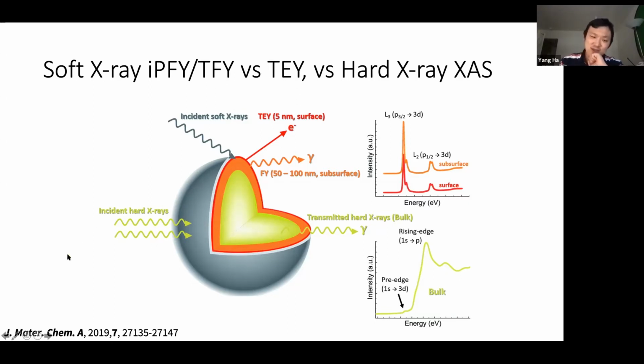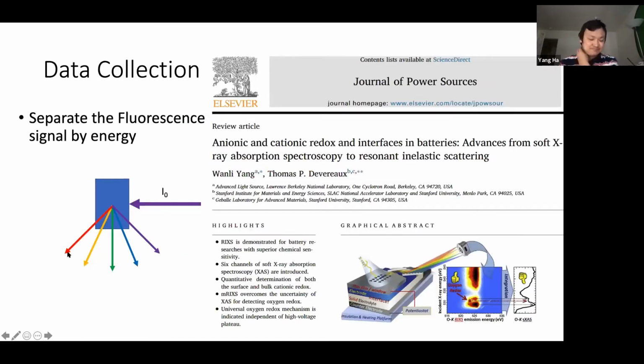And what is more, we can try to isolate the coming out fluorescence by their photon energies. So we can add a grating here at our beamline, and then we can collect it using a CCD detector. So in this case, we will end up with a 2D spectrum. We can have the absorption energy in one dimension and the emission energy in the other dimension. So we really end up with a 2D RIXS map, which brings us an additional dimension, which makes it way better than the traditional 1D X-ray absorption spectra.